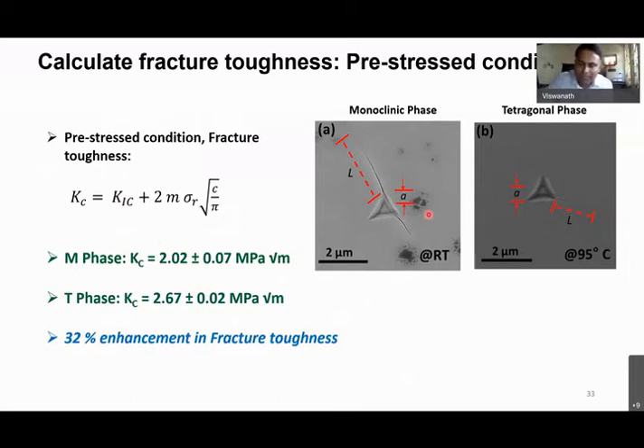So otherwise, what is happening is, the nano indentation fracture toughness that we are measuring, we are not really taking into account the tensile stress of 0.95 gigapascal acting on them, because we are doing the measurement on the platelets which are attached to the quartz substrate. Then we found a literature wherein the residual stress can actually be accounted for in the entire formula.